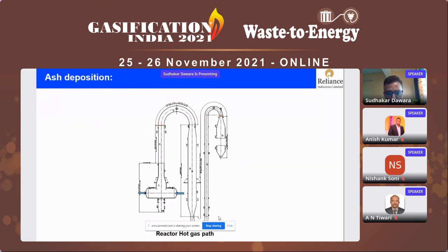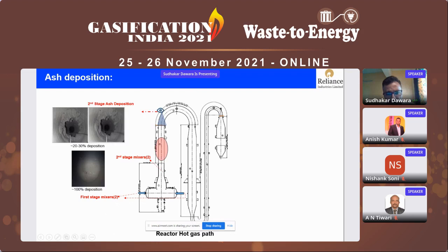So I'll just give you a little more view on this. As I told you, we have two first stage mixers and two second stage mixers. If we look from this point at the top, this is the second stage. Here you can see on the left side the pictures. These are the kind of deposition we have in this hot gas path. In the first two pictures, you can see that it's a good operation. After 65, 70, 100 days of operation, if we have this kind of deposition, we are happy. But sometimes if operation is not correct, if we have some issues managing the feed flux, or maybe some flow dynamics issues, we sometimes have complete blockage of the second stage. You can see in the lower picture, almost 100% of the cross section area is blocked.